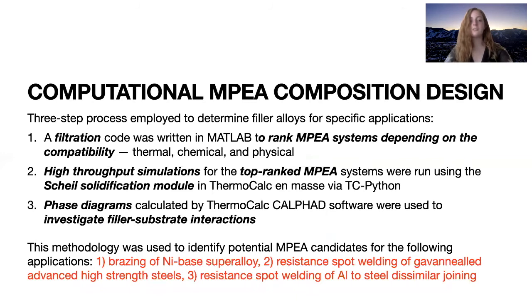So first, our computational MPEA composition design was a 3-step process employed to determine filler alloys for specific applications, which we have at the bottom of the screen. So first, there was a filtration code that was written in MATLAB to rank MPEA systems depending on the compatibility. This compatibility was between thermal, chemical, and physical compatibility. The second step was high throughput simulations for the top ranked MPEA systems were run using the Scheil solidification module and Thermo-Calc via TC Python. The third and final step was phase diagrams calculated by Thermo-Calc CALPHAD software were used to investigate filler substrate interactions. So this methodology was used for the 3 applications described below.